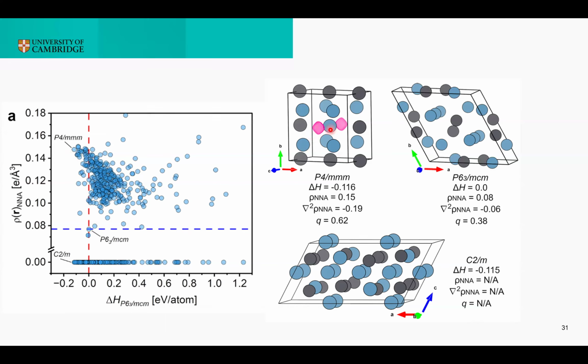So here this pink blob highlights the charge localization. Here you can compare other descriptors like the Laplacian of the electron density that basically quantifies the level of concentration of the electron density around the non-nuclear attractor, so how peaked is this maximum, and also the total integrated charge at the non-nuclear attractor, which is almost here 1 electron. And you see that this new P4/mmm is overwhelmingly more electride than the P63/mcm that is stable at ambient pressure, but then becomes an electride at high pressure, and also way more stable, almost 0.1 electron volts per atom.